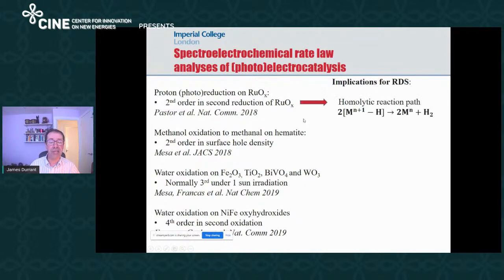It turns out that proton reduction on ruthenium oxide is 2nd order in the 2nd reduction of ruthenium oxide, and that allows us to suggest the reaction is a homolytic reaction pathway. We can apply the same thing when looking at methanol oxidation on hematite. It turns out methanol oxidation is 2nd order in surface hole density, and that allowed us to propose a particular mechanism for methanol oxidation on hematite.